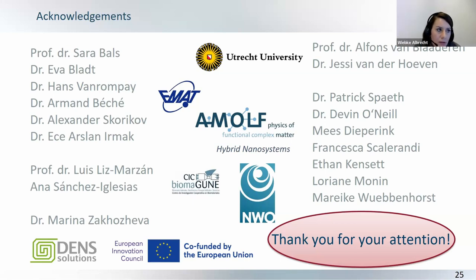Yes, I think that really depends also on, first of all, on the excitation scheme. So, if you have nanosecond pulses, you get these dog-shaped or phi-shaped particles a bit more, because you already start cooling, and you start cooling more of one, the tips of the particles than the middle. So, you have also a temperature gradient. It also depends on the size of the particles, right? So, at some point, you cannot assume that there is a homogeneous temperature distribution anymore. Specifically, if also, already the tips start to cool down faster than the middle. So, I think all of these factors really influence how that works. So, in our case, these particles are very small, because otherwise, we cannot do electron tomography with atomic resolution. So, they need to be very small. So, we can really assume a somewhat homogeneous temperature distribution.